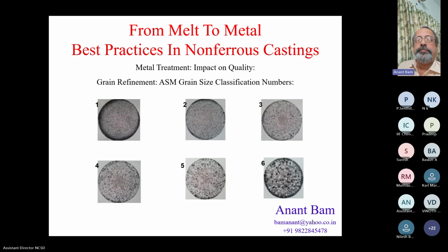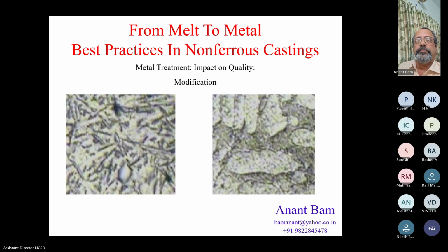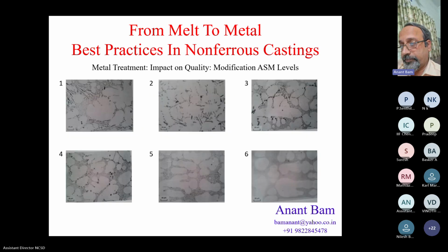Next slide, please. These are microstructures or micrographs depicting modification of silicon. On the left hand side is unmodified silicon. Acicular silicon is seen. On the right hand side is fully modified silicon along with alpha dendrites. Next slide, please.